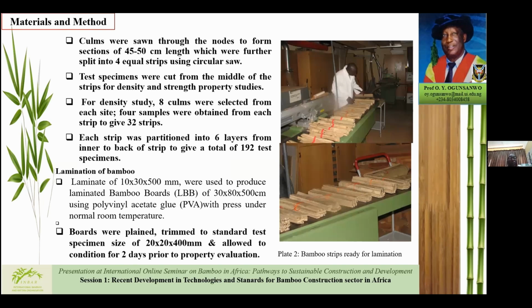During the methodology, culms were sawn through the node to form sections of 45-50 cm length, which were further split into 4 equal strips using the circular saw. Test specimens were also cut from the middle of the strips for density and strength property evaluations. And for density, we took 8 culms from each site, and four samples were obtained from each strip to give a total of 32 strips. Each strip was then partitioned into 6 layers from the inner to the back